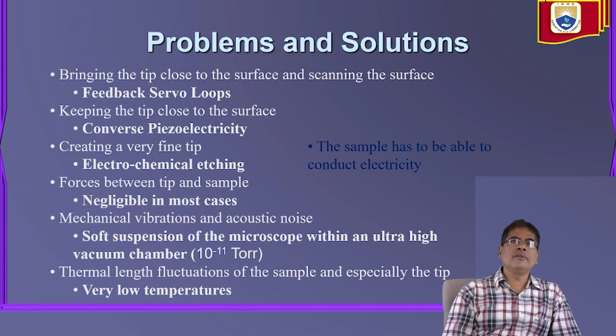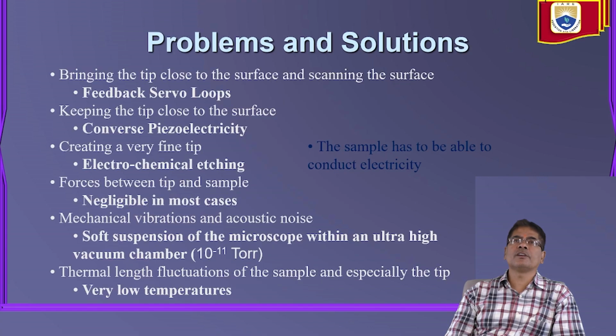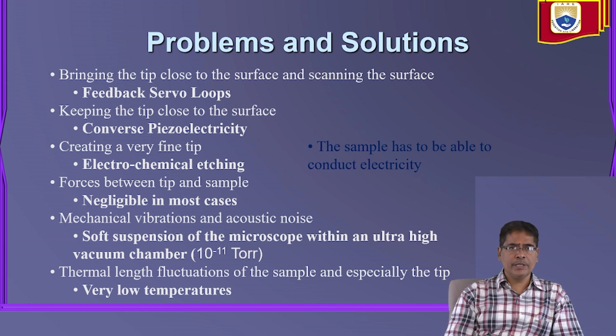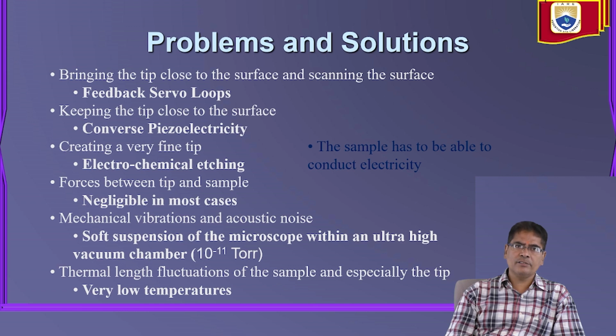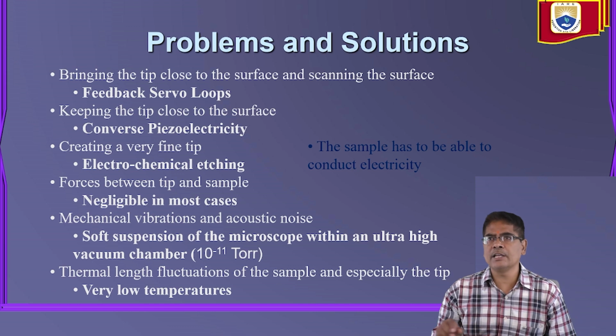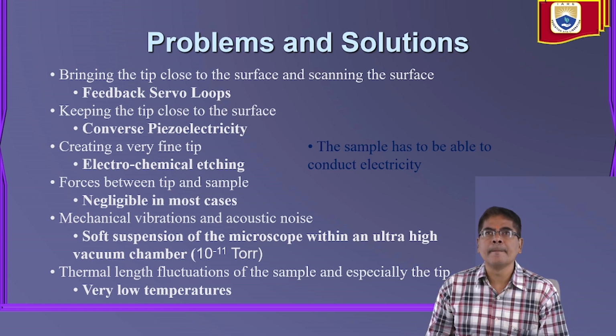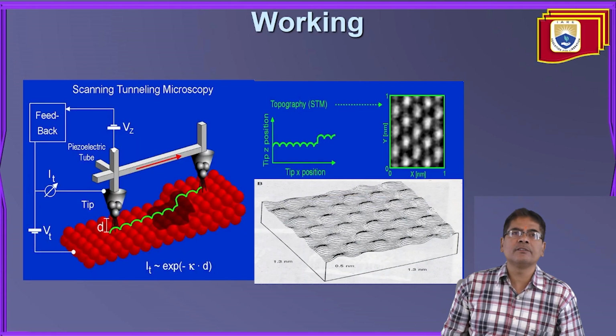So these are some of the problems and solutions. Bringing the tip close to the surface and scanning, feedback servo loops. Keeping the tip close to the surface, this is converse piezoelectricity, creating a very fine tip, electrochemical etching. Forces between the tip and the sample are negligible in most cases. Mechanical vibrations and acoustic noise: soft suspension of the microscope within an ultra high vacuum chamber, and thermal length fluctuations of the sample, and especially the tip, which is maintained at very low temperature, right? Very low temperature. The sample has to be able to conduct electricity, right? So this is how the working takes place.